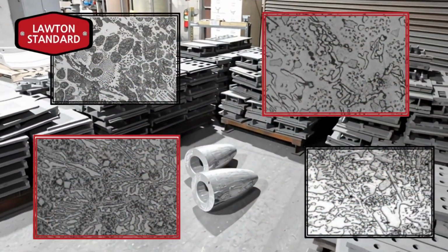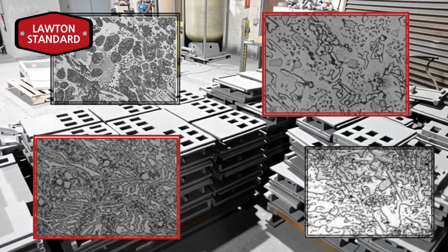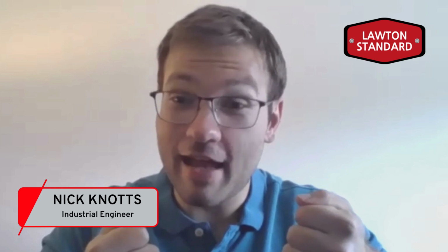That it lacks true tensile strength. So if you actually pull it in tension, it doesn't have a lot to hold together. It does not do great in compression. It can handle it. It does terrible against uneven loading. If there's parts of the casting that are getting more loading than other parts, no, it's not going to happen. It has essentially no impact toughness. I think some people have actually hit Charpy bars out of white iron, and I think the toughness was something like 3 joules. It was basically non-existent, right?